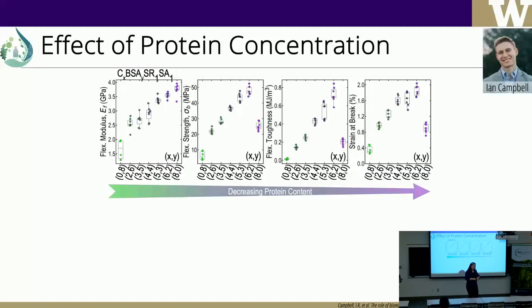Because you may have Maillard reaction. If it's done under heat, you might get Maillard reaction. But these are quite mild conditions. Like in this particular case, we're pressing at 80 degrees C, and I want to say 1 MPa. So that is a good suggestion, absolutely. And I do think that there's also fiber level interactions, not just the hydrogen bonding. But let's see if we have Maillard reactions, maybe.